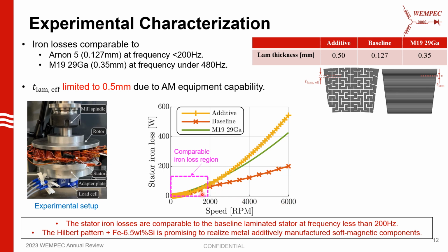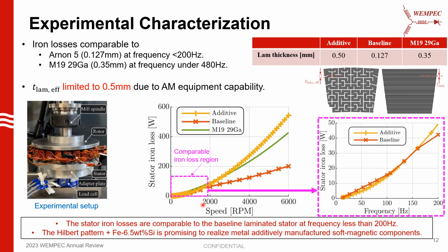It can be seen that the iron losses between the baseline and additive stator are comparable up to a speed of approximately 2000 RPM. Although these speeds seem modest for electric machines, if we look at the frequency, it shows that the iron losses are comparable up to a frequency of approximately 200 Hz. This is a significantly high frequency and translates to a low speed for this particular machine since the machine has a high pole count of 8 pole pairs. So these results show that the Hilbert pattern, along with 6.5% silicon steel, is very promising to realize metal additively manufactured soft magnetic components.